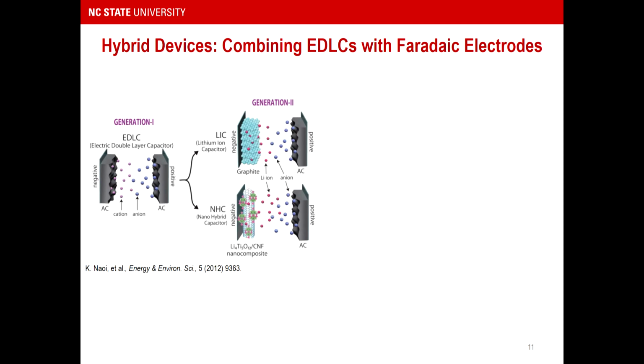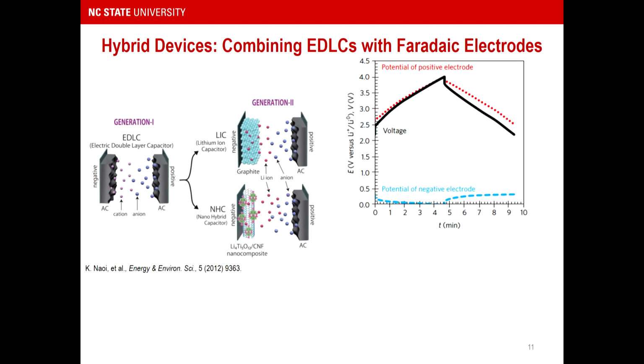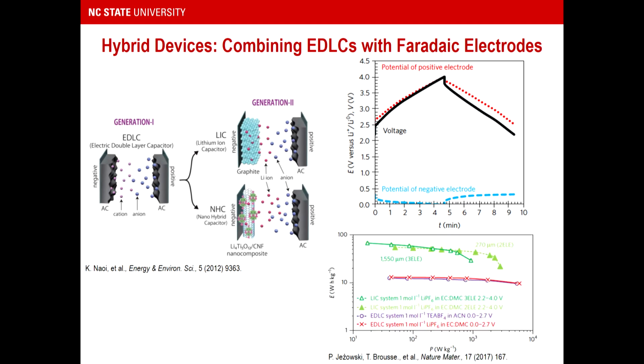And so when we combine them, activated carbon electrode, for example, with graphite or a lithium titanate anode, we have the continuously varying potential of the activated carbon, paired with the nearly constant potential of something like lithium intercalation in graphite, and now you have hybrid devices that can offer around 70 watt-hours per kilogram. That's on the basis of the electrode materials. So in the packaged device, it would be a little lower. Nevertheless, these types of hybrids still suffer the power limitations of the battery-type electrode.